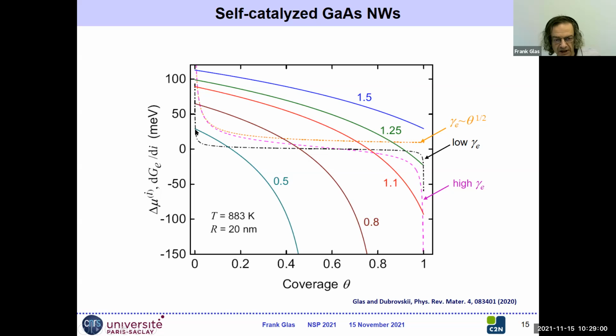For low content, we have our standard picture. Say we have first here a first intersection, so it's a critical size, and then we have a stopping size. If we increase the content, we can still have a stopping size. And here we see that for the three possibilities for the step energy, we have a stopping size. It's still the case here. Of course, with a very large content, we don't get a stopping size. We're in the case where the chemical potential will not intersect the derivative of the step energy before the monolayer is completed. So here we grow a full monolayer, nothing new.